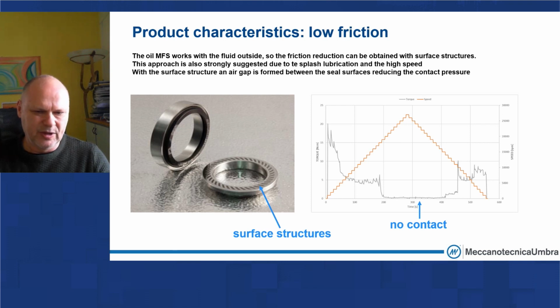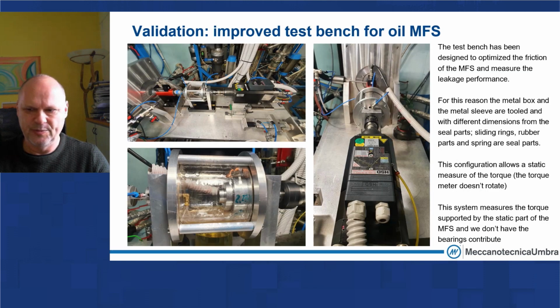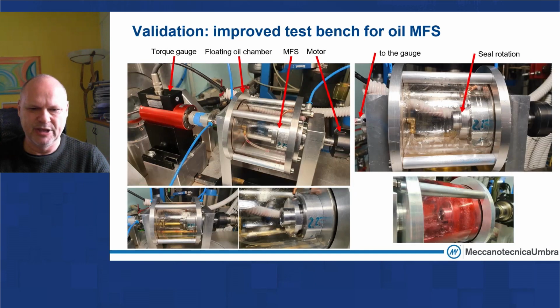This is an example of a mechanical seal for helicopter transmission, and this is the graphic where it's possible to see the friction of the mechanical seal when the speed increases. This type of geometry is called grooves and has the role to separate the faces and avoid any contact between the two faces. So avoiding the contact, we reduce the friction close to zero. We apply this technology to an oil seal for electrical motors. We also tested this solution in our test benches.